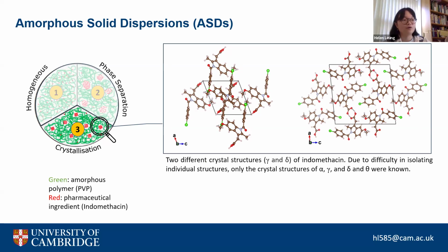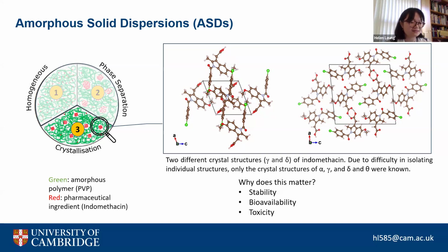There are different crystal forms, which we call polymorphs, and those different polymorphs might have different stabilities, different bioavailabilities, and importantly, different toxicities. And for those of you who are interested, probably the most famous example of where polymorphism in a drug has gone wrong is in ritonavir, where essentially at the late stages of that drug, an unexpected polymorphic form was found in the manufactured product, and this had non-ideal effects.